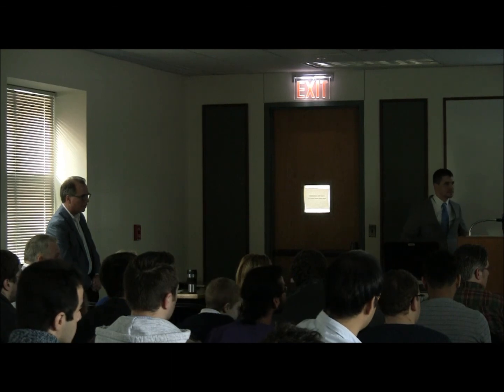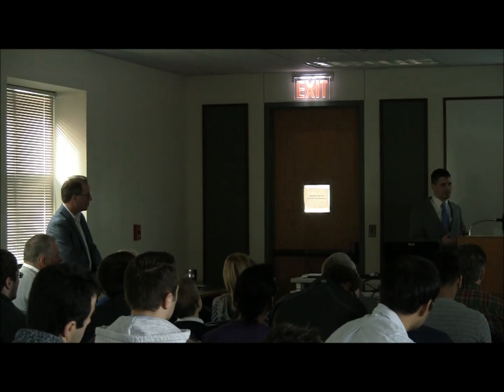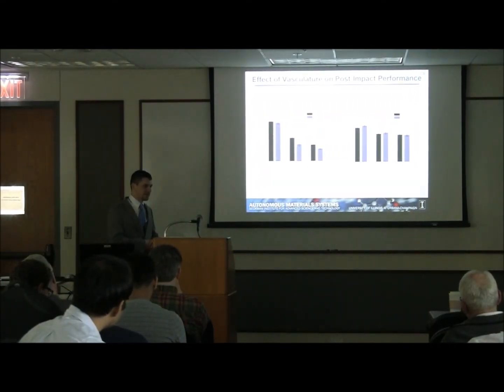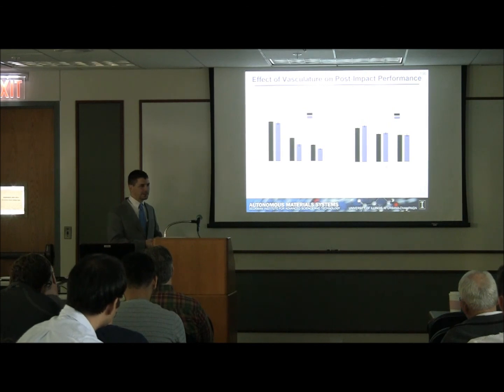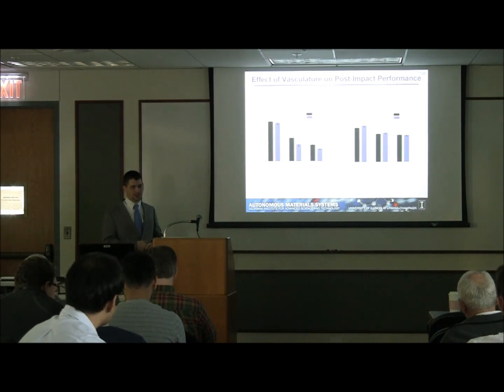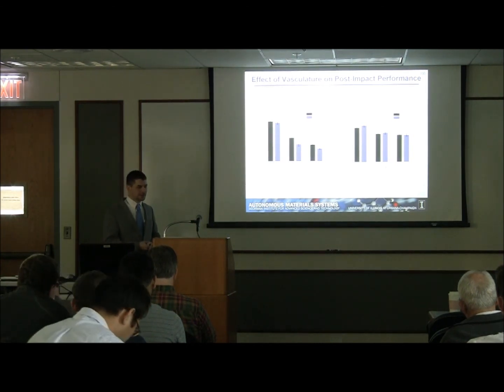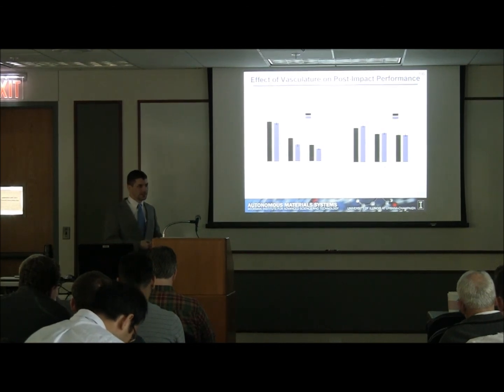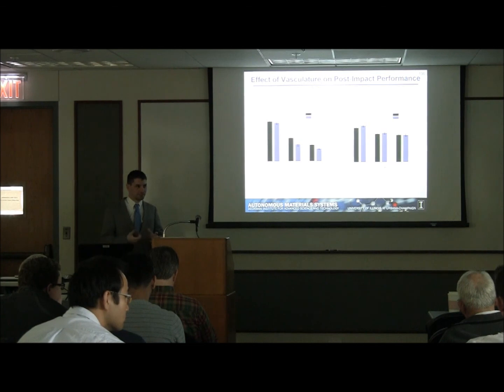You also did a lot of work on the composite system. Did you ever use the same system? I did actually venture into creating composites and showing, using some sort of reference test, that we could heal some small amounts of impact damage using vacuum infiltration of epoxy agents and then healing the composite at high temperature. I include that in the appendix of my dissertation, but only that slight demonstration was ever really pursued. I included it in the future work of my dissertation, because I think it could be a really useful healing technique moving forward. I just didn't pursue it.